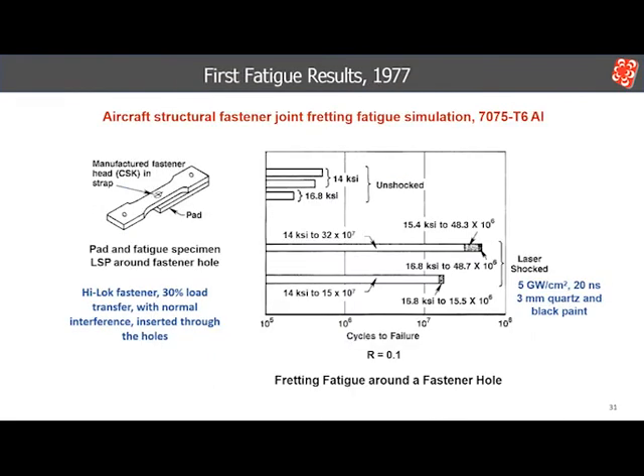In 1977, we were beginning to look at other mechanical properties beyond strength, hardening, and corrosion. Steve Ford suggested we examine how laser shocking might affect fretting fatigue in riveted joints in aircraft structures. As shown on the left, the fretting fatigue test was based on a dog bone-shaped tensile specimen with a rectangular pad clamped to it using a standard aircraft fastener tightened for 30% load transfer.